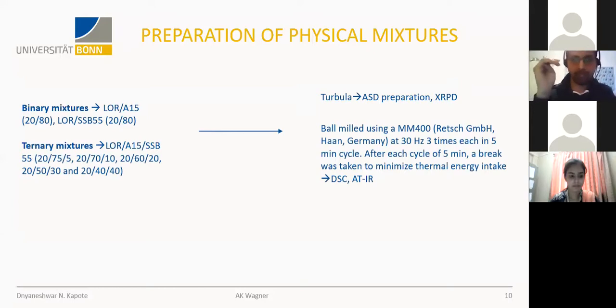And for DSC and ATR-IR, we used a ball mill at 30 hertz, three times in 5-minute cycles. After each 5-minute cycle, a break was taken to minimize thermal energy intake, which is quite common after ball milling.